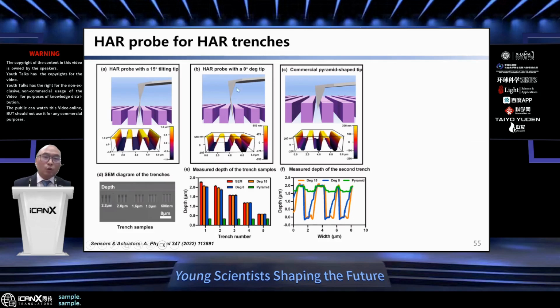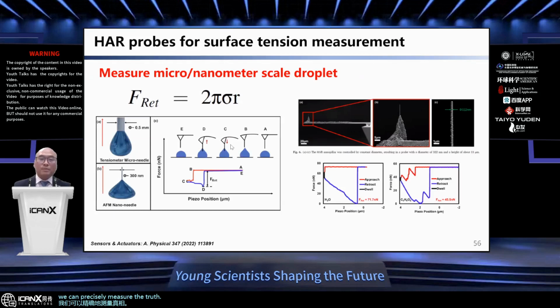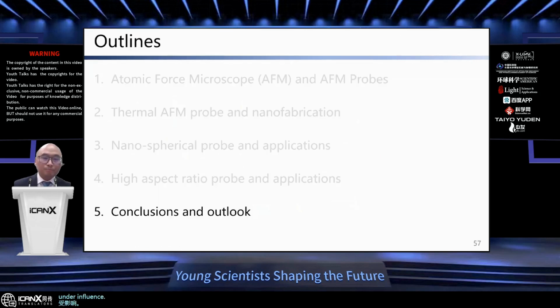If you're using a non-tilting tip, it's still hard to get to the bottom, because the AFM probe cantilever is not perfectly parallel to the substrate. But with the AFM probe with a tip at the desired tilting angle, we can precisely measure the trenches. We also demonstrate the application of these high aspect ratio probes for measuring micro-nanoscale liquid droplets, and for measuring the forming mechanism of rain droplets under the influence of contamination.